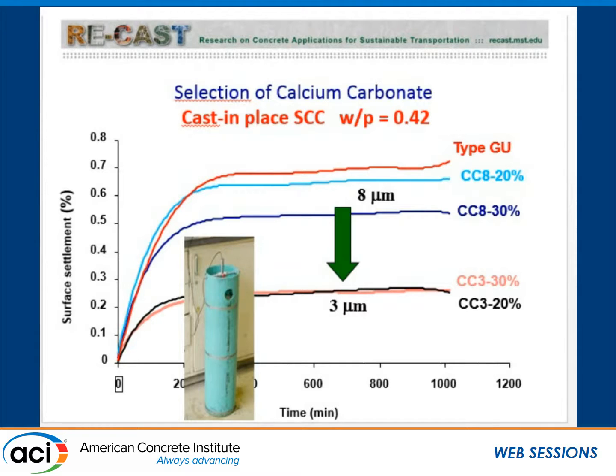But the magic number where we would like to get with the settlement test is 0.5. And we see when you go from 8 micron D50 to 3 micron, you get a lot of reduction of settlement, and 20% was good enough in terms of settlement. And that's important because when you are designing these concretes, you want a very high stability, especially if the water binder ratio, in this case water powder ratio, is relatively high, because that will give you stability, static stability, dynamic stability, but also will allow you to reduce the dosage of viscosity modifying admixture. So you could think of that as a powder addition that could reduce some of the VMA that is incorporated in SCC mixtures.